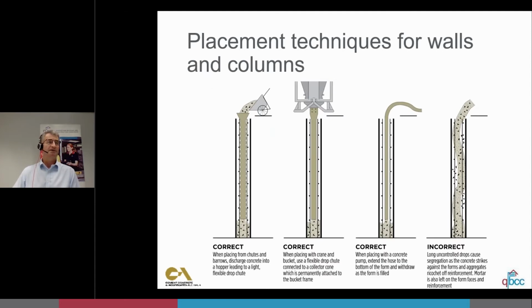So this page shows piling or columns, and again, it's just demonstrating the use of this funnel or tremie to make sure that the concrete is not free falling any distance. And certainly if you're doing a pile and you're placing concrete underneath water or underneath drilling mud, for example, then that tremie would have to go underneath the surface of the concrete that's already been placed. So as the concrete rises, it's got a nice clean profile and displaces any water or drilling mud up above it. And you can see the incorrect method on the far right here, where it's just free falling and potentially leaving, as in this picture, spaces where the concrete just hasn't flowed out and completely filled the form.